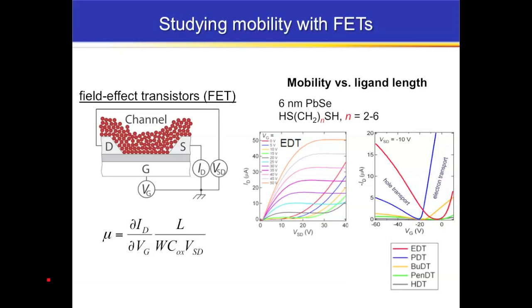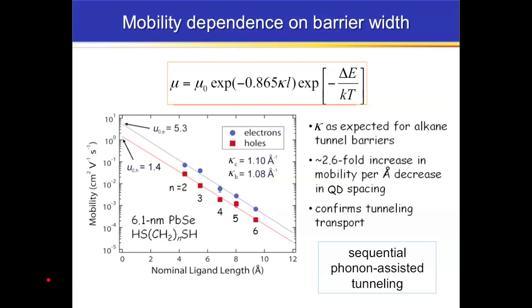If you look at the data, this is the drain current, this is the gate voltage. EDT, the shortest ligand, is the red, and then HDT is the longest ligand. It's down here next to the axis. You can see that the slope gets progressively smaller and smaller as we increase the ligand size. That's telling us basically that the mobility is getting larger and larger as we move to smaller and smaller ligands. If you plot this on a log plot, you can get a very nice linear looking slope, or really it's an exponential, for both the electrons and for the holes.